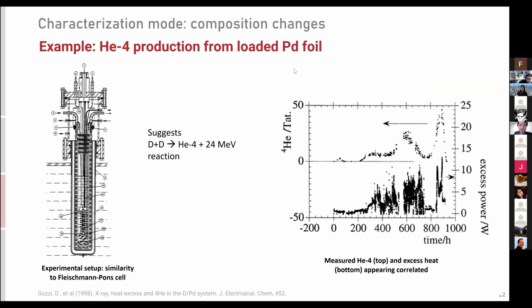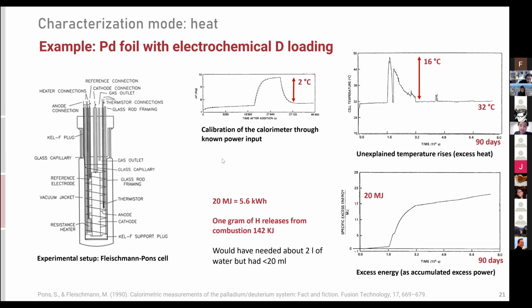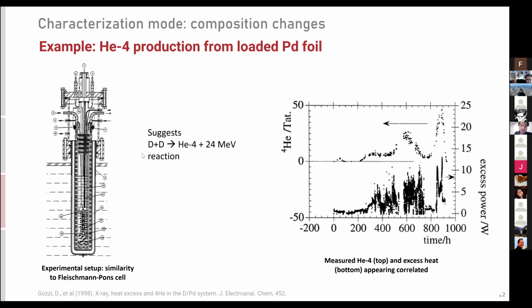There were other measurements. You'd say, well, can we have other types of measurements, maybe more precise measurements that give us not just heat, but other kinds of indicators? If the hypothesis was correct, that this large heat was caused by deuterium fusion, the deuterium in the heavy water, then you would expect one out of several kinds of products. We've seen earlier there are different ways the fusion reaction can result in products, and there are actually three ways that are known conventionally in the deuterium reaction, and one of them leads to helium.